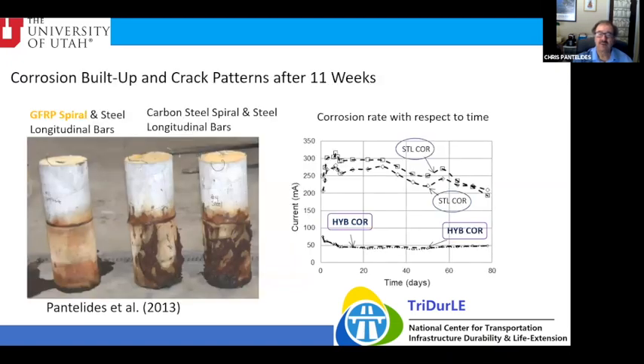So here's the corrosion built up and the crack pattern after 11 weeks. You can see on the left here, this column has fiberglass spiral and steel vertical, and you can see practically no cracking. And these other two are the ones that are reinforced only with steel. They're all steel ones, carbon steel. Here you can also see that the carbon steel actually has a lot more current through it, whereas the hybrid actually doesn't let any current come through.